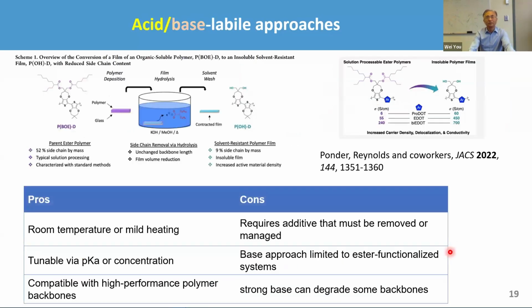Okay, so the last one is the so-called acid-base approach. This particular example was done by Professor John Reynolds' lab and also his student James Ponder. They published a few papers in the past few years using this interesting ester. Okay, we all understand that an ester can be cleaved using acid or base, or hydrolyzed. So in this particular case, they're using the polymer decorated with ester. They're using base to remove them in aqueous solution and methanol, then you end up with this particular material that's becoming side chain free, more or less. And then they were able to show that by using this approach, you can actually end up with a higher conductivity afterwards. So this seems to be a very good approach, right?